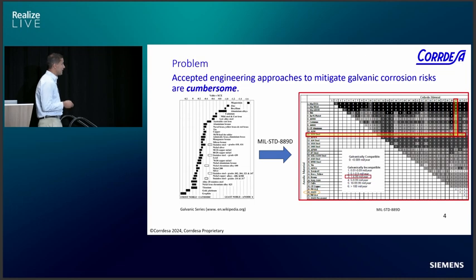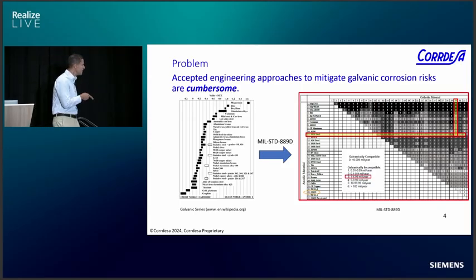The MIL standard is what the DoD is now using. They said it is time for us to come up with, or to use, a standard so that everybody, OEMs, can use a common ground. And this is really simple to use. In the table, as we see here, we have this column over here with some materials, and another column here that represents the same materials. So, for example, 11 is 11 over here. If we want to determine the corrosion rate between steel and this stainless steel over here, it is basically just a matter of drawing a line from 11 and intersecting it with the 30. And that says that the corrosion risk is number 3, which means we are going to have a corrosion rate of between 1 and 5 mils per year.